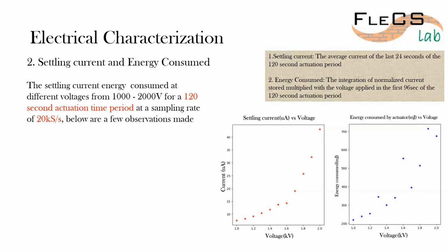One of the interesting observations in this current versus voltage plot is that you would assume it should be linear, because given that it's leakage current for the same capacitor, the resistance should be constant, which means the current-voltage characteristic should be linear. But it's basically linear in two different regimes. There's something happening at 1.6, 1.7 kV, where there is a specific resistance on one side and a different specific resistance on the other. So that's an interesting thing as well. We're trying to observe what those two regimes are and why that is happening. That's all I have.